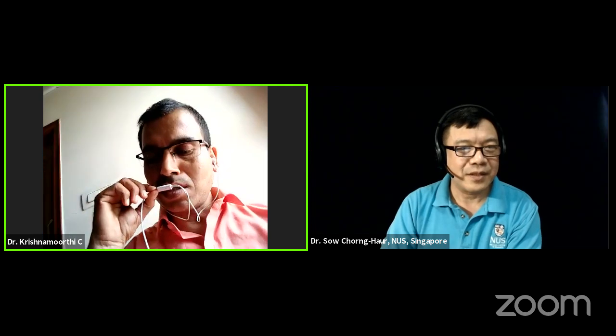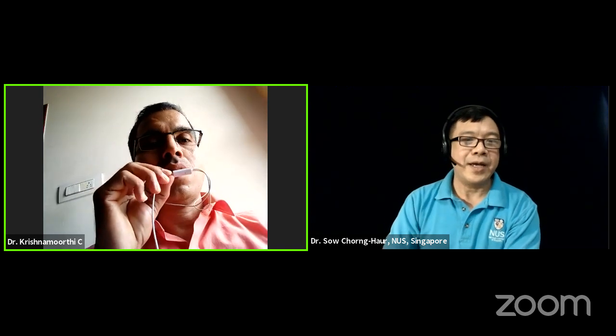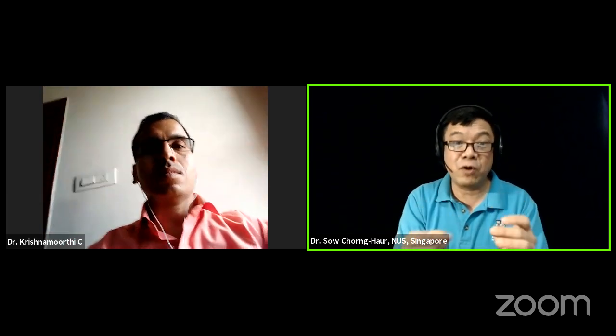The first question is how to create electric contacts for the nanowires with the electrodes? What we do is we use e-beam lithography. My students will put the wires onto a substrate and then go to the e-beam lithography system, so you know where the wire is. You can use e-beam to define the polymers, and then you do all the usual lithography process, but you know where the wire is. Then the gold electrodes can be deposited on top. Sometimes we use mixtures of titanium and gold, or different choices of electrode that will make the contact better. So basically, e-beam lithography.